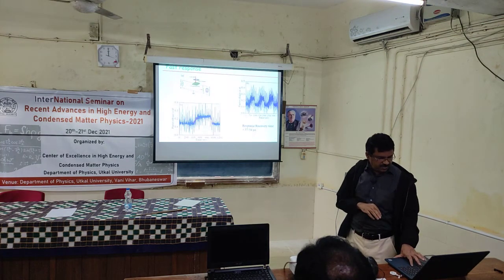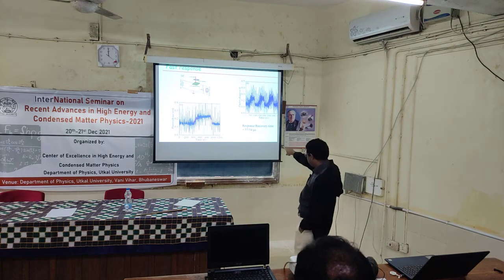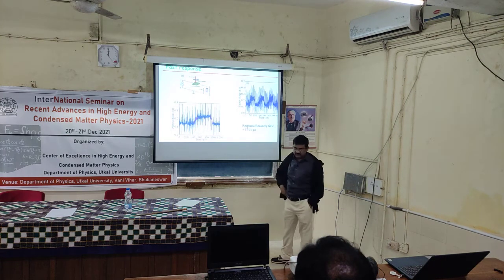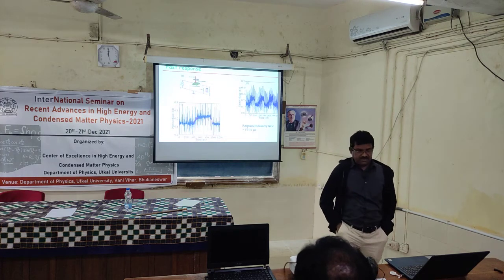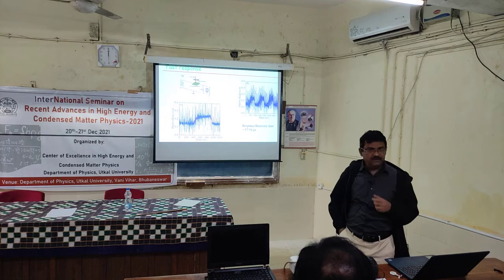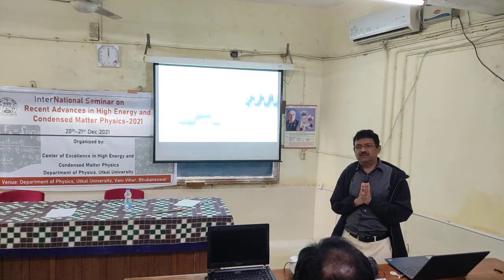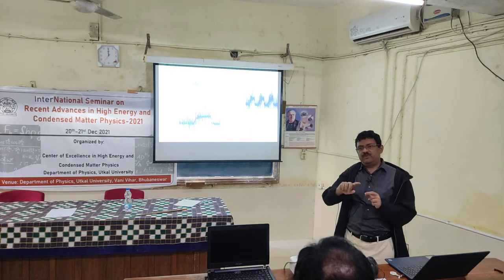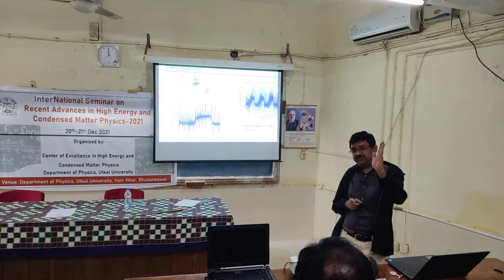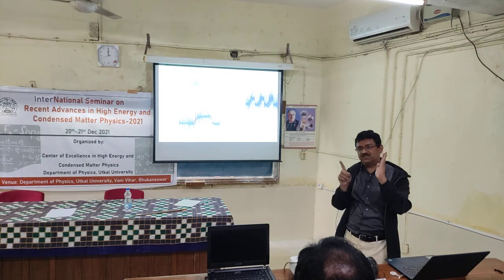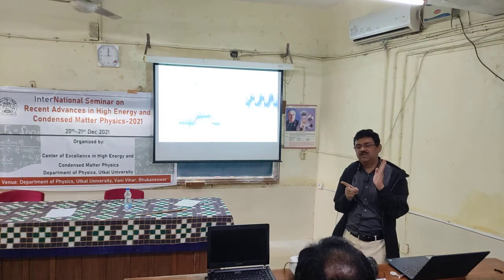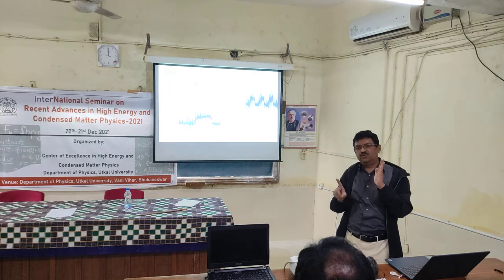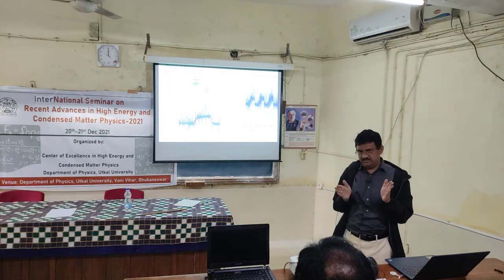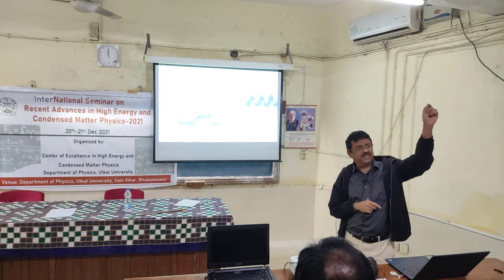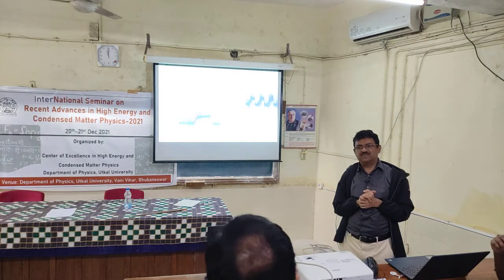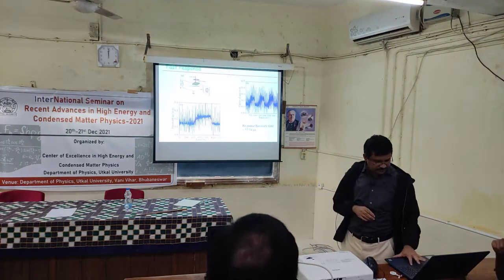I will skip this. The bottom line is that now we can go much faster. The response time is 57 microsecond, and recovery time is 34 microsecond. So by playing with the mobility of the counter semiconductor, with my SnSe2 fixed, I am able to tune the response time or recovery time of the device from second to microsecond, which is 10 to the 6 times faster. So this is how it is.